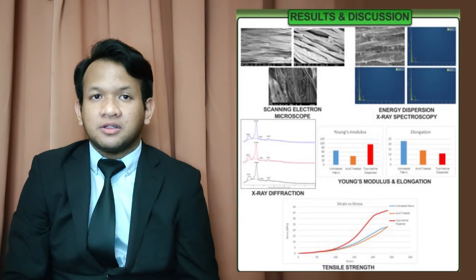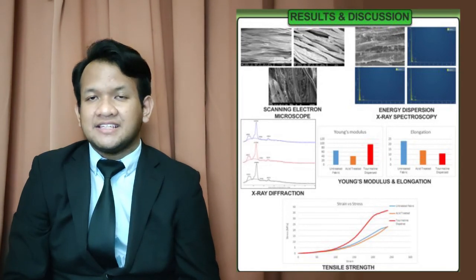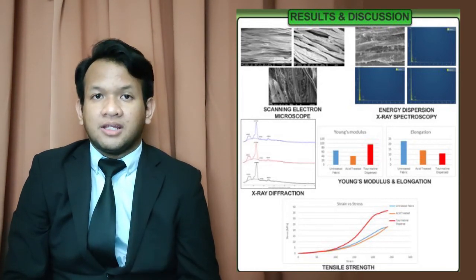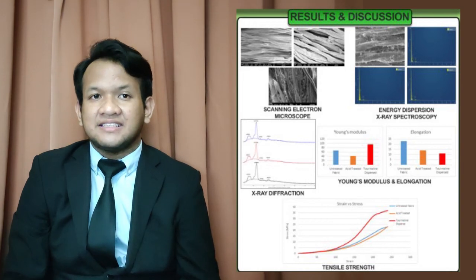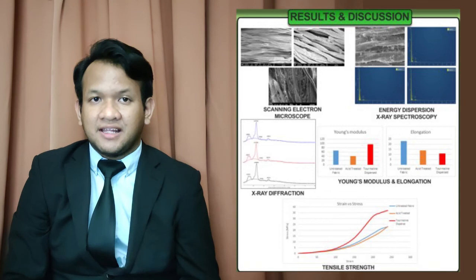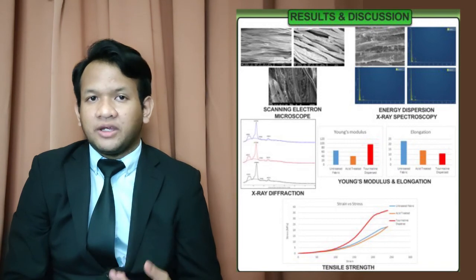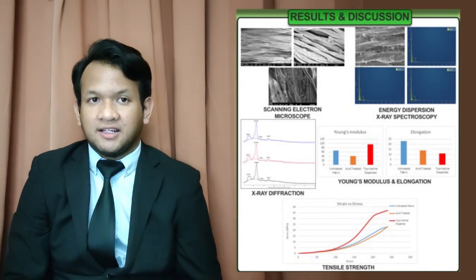There is also an enhancement of mechanical properties in the tourmaline-infused fabric. The stress versus strain graph showed that the tourmaline-dispersed fabric produced a significant change in tensile strength compared to the untreated and acid-treated fabric, where the tourmaline-infused fabric has a higher tensile strength at 37.5 megapascal compared to acid-treated with 23.2 megapascal and untreated fabric with 23.15 megapascal.